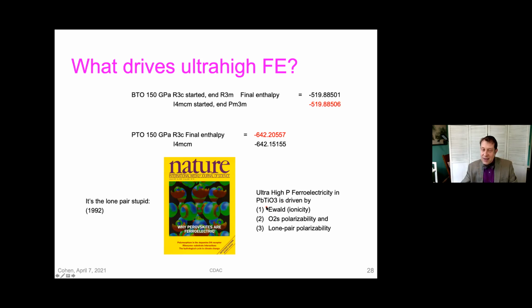So in the end, I think you have the Ewald part drives things off center, like we've always known. You have this polarizability of the O 2s states, which I would say is not really fully understood still, but it's surprising. And then, the key thing here is this lone pair polarizability, I think.